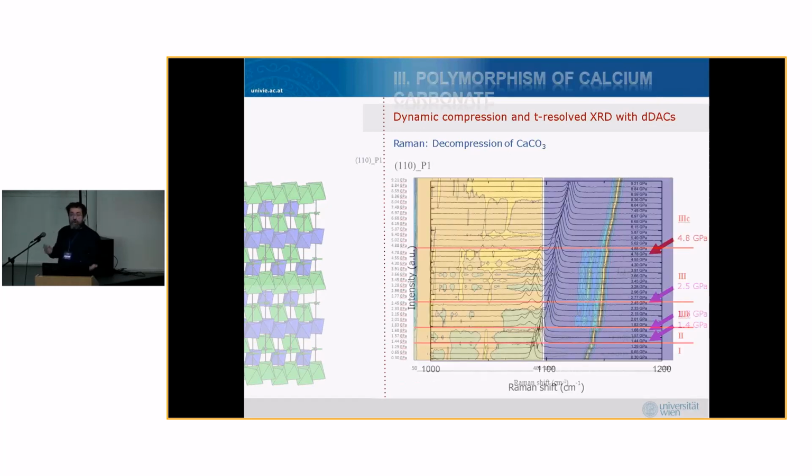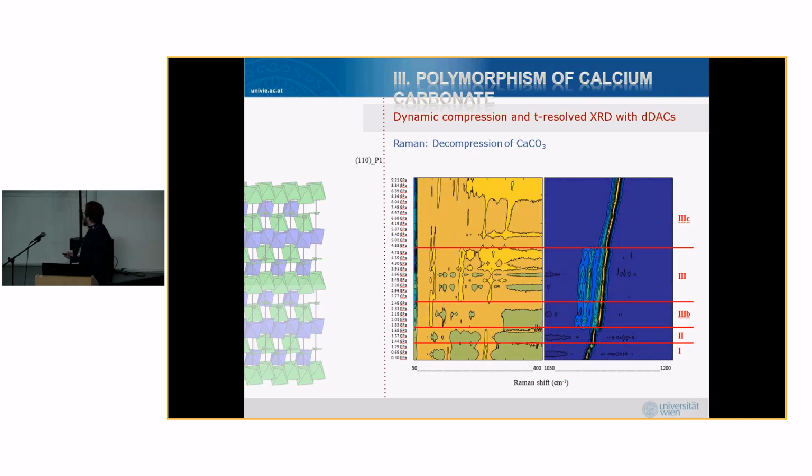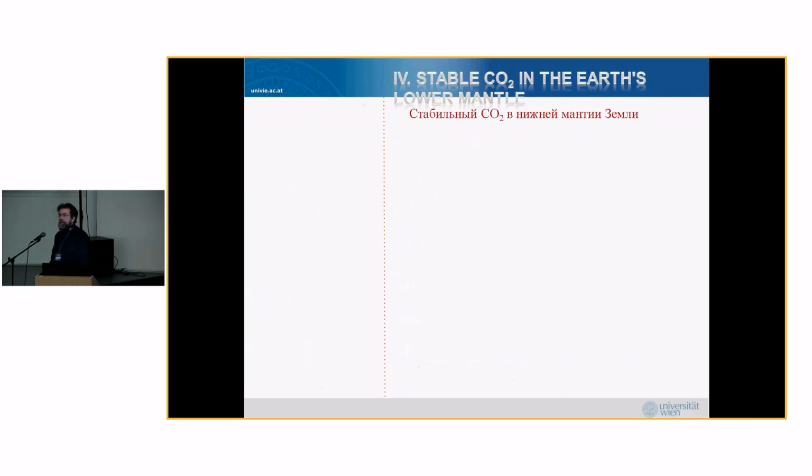So plotting all these Raman spectra that we have measured together, we can be pretty convinced that we now have this phase 3C, because it's different from phase 3 and phase 3b. This difference has been established anyway, including by X-ray diffraction. That means it is just an example showing you that polymorphism, even in ranges which are not that extreme, can be very surprising sometimes, and this is the one example I wanted to show here.